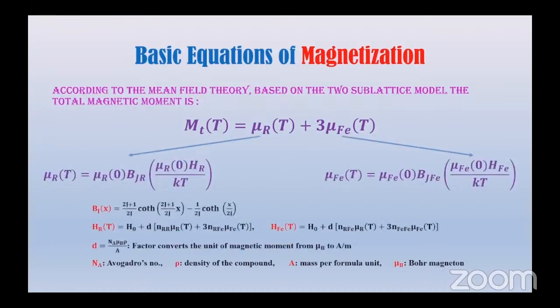Basic equation of magnetization. According to mean field theory, based on the two sublattice model, the total magnetization is equal to the molecular field of the rare earth plus 3 iron sublattices, where the Brillouin function controls the temperature dependence of each sublattice moment.